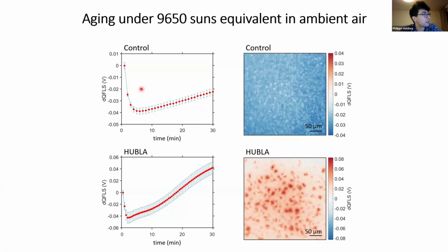And this is sort of an in situ aging. You see here the control has a drop very quickly in photoluminescence and improves a little bit over time. And for the HUBLA, we also see this drop, but then a significantly stronger improvement. So here on the left axis, you see quasi-Fermi level splitting, which you can correlate with the PL intensity. And then on the right, you see differential quasi-Fermi level splitting of the maps. So that's between the first and the last map. And then you can associate sort of an ideal VOC enhancement for the map. And you can see that the HUBLA has regions of very strong improvement on the films where the PL increases significantly.